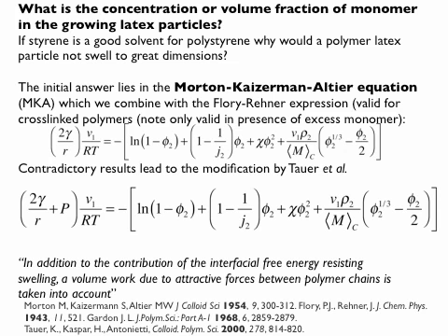So I see I have got an ln(1 minus φ2) volumetric term in there, and that volumetric term is related to the volume fraction of polymer. So 1 minus the volume fraction of polymer is in a way the same as the volume fraction of the monomer. And then I've got plus (1 minus 1 over J2).